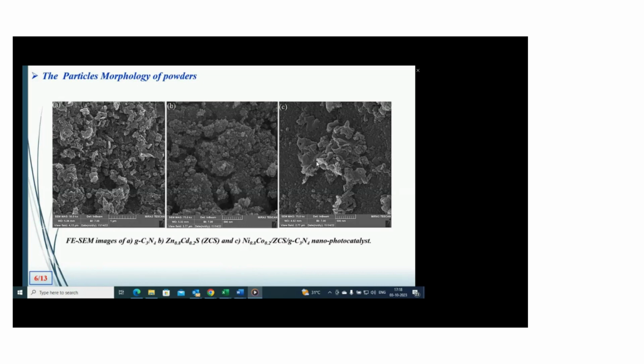However, because of the minimal amount of NiCo nanoparticles in the sample, it's hard to distinguish them in the microstructure. However, the existence of these nanoparticles was further proved by EDAX analysis.